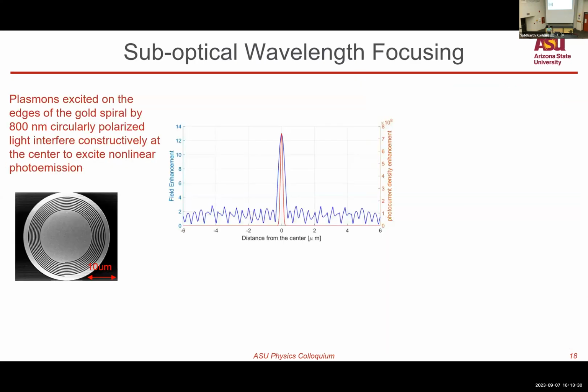The first one is trying to focus light into a very small spot. We use these plasmonic spiral structures. These are spirals etched into a thin film of gold over a silicon substrate. When we shine 800 nanometer circularly polarized light on these structures, that light excites plasmons along the spiral edges, and these plasmons travel towards the center, and they interfere constructively at the center. And if you plot the field enhancement, or the field of light, as a function of the distance from the center, you see that the plasmon interference causes a very strong peak at the center.